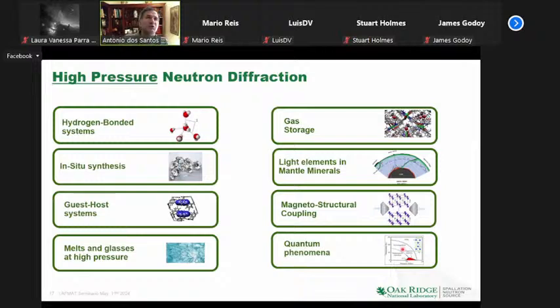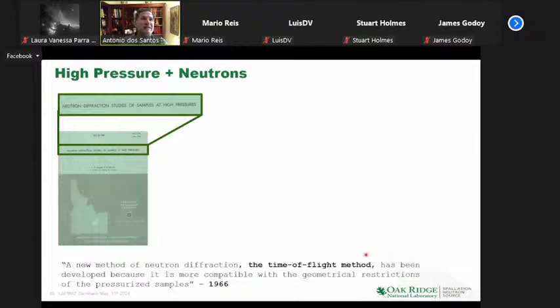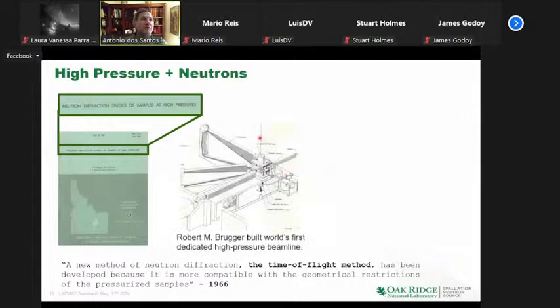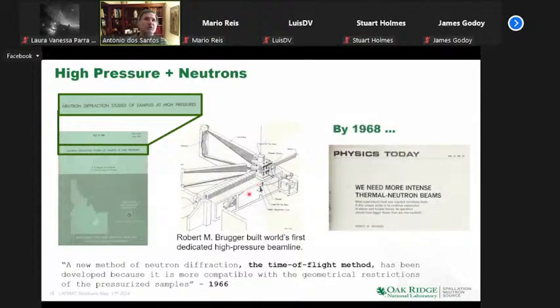Now, this is certainly not new, why we need high pressure and neutrons. It was actually recognized almost at the same time as the time of flight method was developed. And Brugger said that this method has been developed as it's compatible with geometrical restrictions of pressurized samples. And indeed, it was easier days. Within years, the first high pressure diffractometer was built on a reactor, but using a pulsed source. That's that chopper here. And there's a little pressure cell. And within 2 years, they were asking for more intense neutron beams. And this struggle is going on today, as I showed you earlier, with the ongoing proton power upgrade for us and for many other facilities.